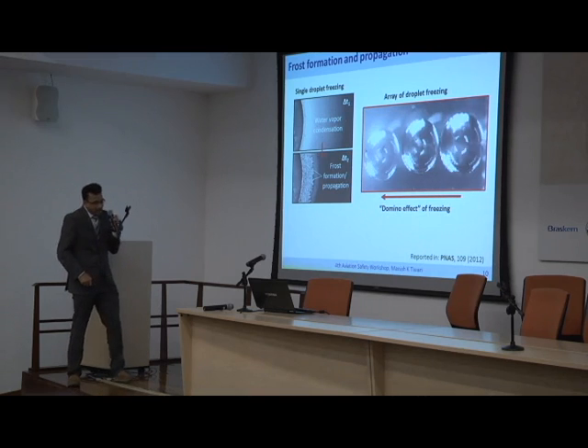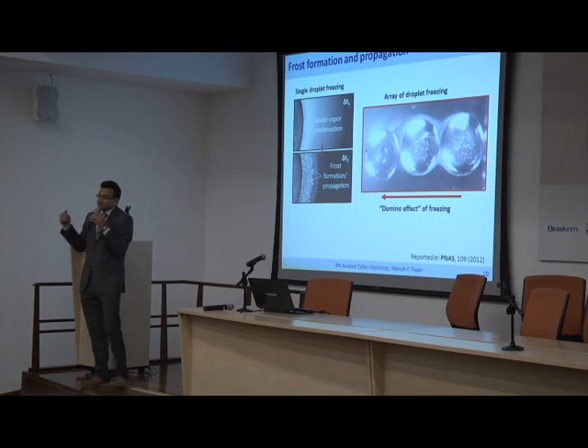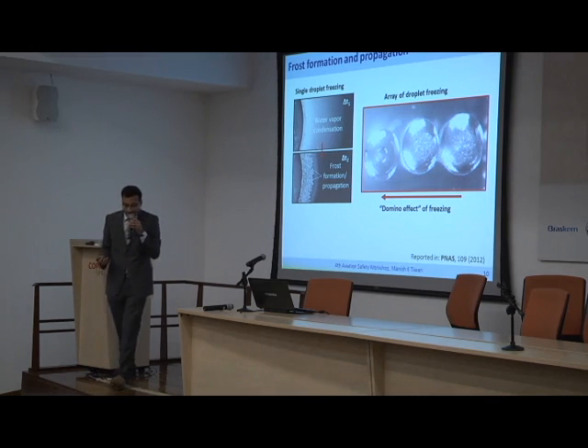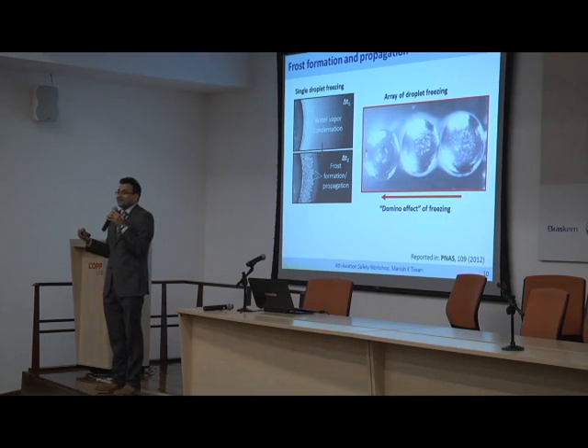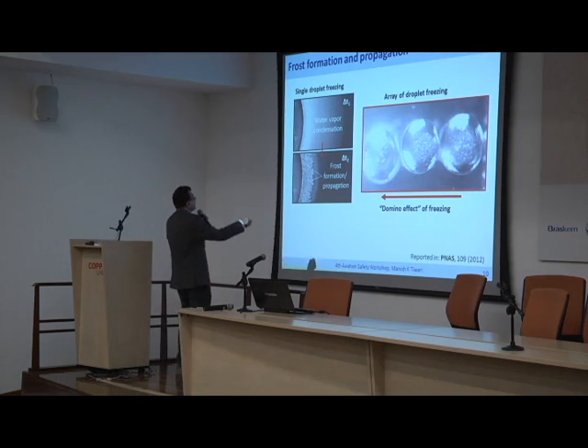Okay. And if I do this experiment, in this case deliberately on an acrylic, which is a thermal insulator, I make sure that the heat cannot go through the substrate either. So where is the heat going to go? It's going to be absorbed by any of the remaining liquid, which is going to evaporate at that point. But now think of this vapor. It comes out and it's in a minus 15 degrees centigrade climate. It cannot stay as vapor. So what does it do? It condenses down again.